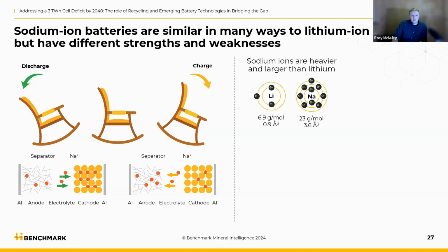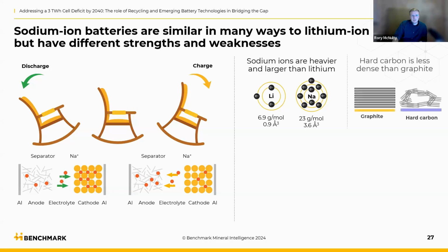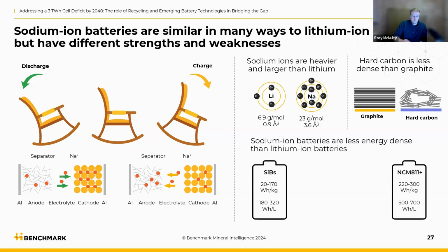Some key differences between lithium and sodium are that the sodium ion is significantly heavier and larger than the lithium ion. And at the anode side, sodium-ion batteries tend to use a hard carbon or a soft carbon amorphous structure, whereas lithium-ion batteries use very well-ordered graphite. This hard carbon is much less dense than graphite is, and the result of this is that sodium-ion batteries, generally speaking, have a lower energy density than lithium-ion batteries.